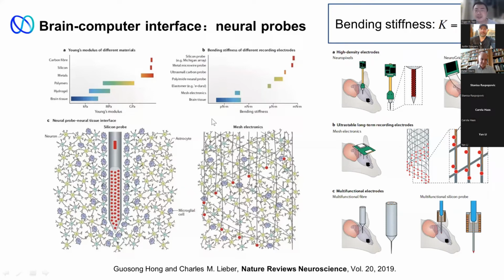But the Young's modulus is not the only thing determining how bad the immune response of those probes is going to be. There's another thing, in my own opinion probably even more important, which is the bending stiffness, or in a very simple way to explain this, how soft they are. So this is a very simple equation. K is the bending stiffness, E is the Young's modulus. If you already choose a material, this one is set, but the bending stiffness is proportional to t to the third, t is thickness here, which means if you reduce the thickness, you can reduce the bending stiffness a lot.